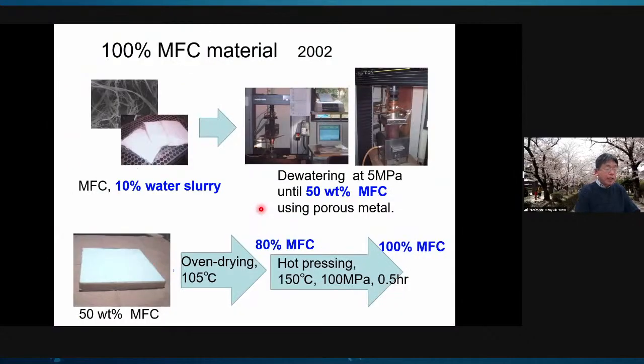At first, I made a 100% cellulose nanofiber material using microfibrillated cellulose donated from Daicel Chemical. We squeezed out water by pressing using a porous metal. After that, we oven-dried the cake and hot pressed it at 150 degrees and 100 megapascal for 30 minutes.